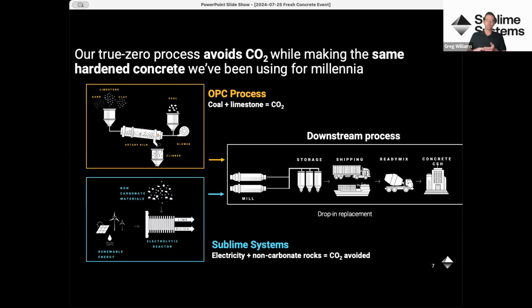So there are really two main reasons why this process is so CO2 intensive. Number one, limestone, when it thermally decomposes inside the kiln, releases roughly half its weight in CO2. So that's source number one: all that CO2 is trapped in the rock. The second source is the burning of the coal and natural gas. So Sublime's way of making cement, we address both of these.